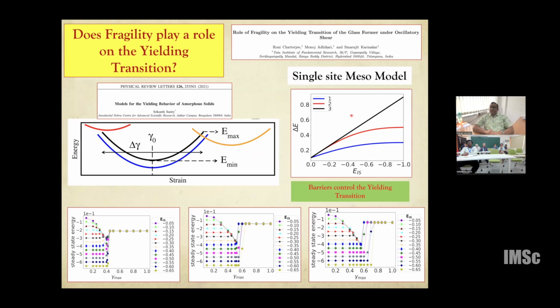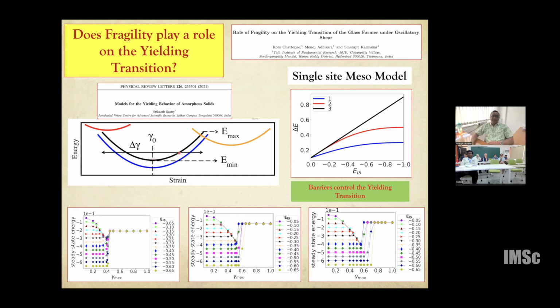But these observations can actually be explained if you do some sort of mean field calculation. This mean field modeling was first proposed by many people, and then subsequently Srikant proposed a new single site model for an amorphous solid and its yielding behavior. So the idea is that you can think of the whole amorphous solid as moving in various energy landscapes. For example, at zero strain you are in this energy landscape, given by this black curve. As you strain the sample, the system goes up in this energy landscape and then topples to new energy minima. So maybe this one, but if you do a reverse shear, then you can access this red minima. If you put in a few such rules, then more or less you can reproduce all this oscillatory shear phase diagram of an amorphous solid.